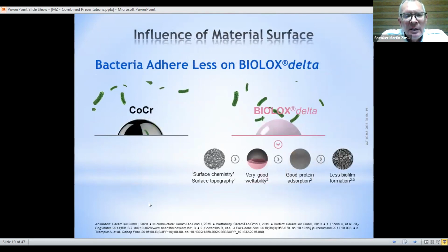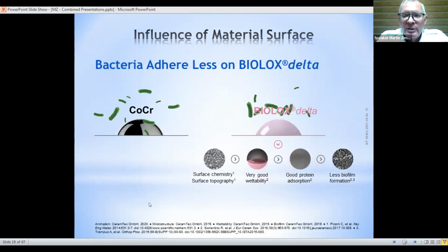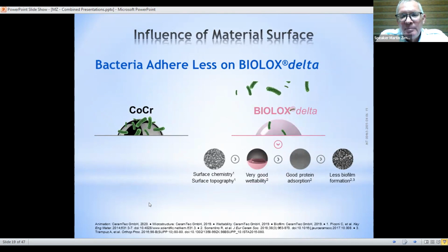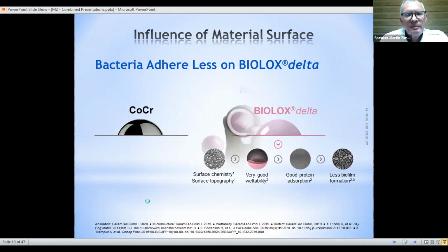I think it is well known that the surface chemistry or the surface topography of a material influences the wettability of the material in vivo, which has an impact on the protein adsorption, which enhances the protein adsorption and reduces the formation of the biofilm. And we can demonstrate, thanks to this in vitro study, that at the surface of the Biolox Delta material you have less formation of biofilm as compared to cobalt chrome.